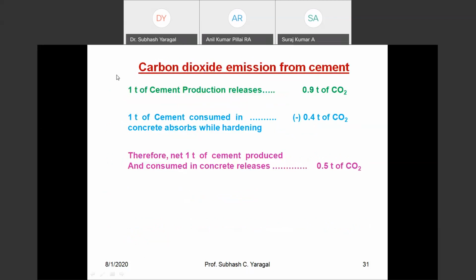So I'm coming back to sustainability. If you look at the production of cement, the carbon dioxide that we are emitting: if you produce 1 ton of cement, approximately 900 kgs or 0.9 ton of CO2 is emitted. Now, when you produce the concrete products using cement, we may have absorption of CO2 from atmosphere during the process of hardening. Therefore, minus 0.4 ton, around 400 kgs, goes back into the body of concrete. So effectively, if you are producing 1 ton of cement, you are letting off around 500 kgs of carbon dioxide into the atmosphere.